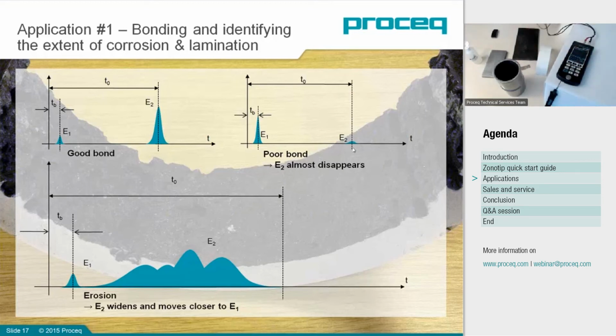Now, going back to the example that I've got for you here today, as you can see, there is a significant amount of corrosion on this particular pipe. So first thing I'm going to do is apply a small amount of coupling paste and start the scanning process. As you can see, I've got a peak right about there. As I move this across my pipe, you can see how the peak changes and comes back. At the same time, it also tells me how deep this particular flaw or crack or corrosion area is within my sample. And it's really easy to identify applications and problems like this.